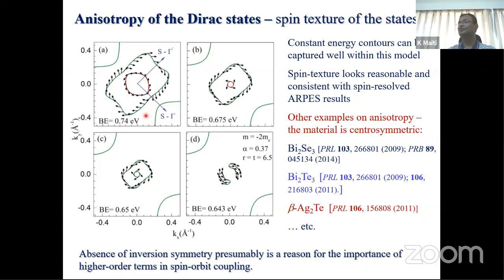Okay. So the conclusion that we can draw from this study is that the Dirac node that people have found so far in various studies is actually occurring at a S point, which has a finite momentum, not at the gamma point. And the anisotropy that we find can be explained by this higher order, which could be because of the lack of inversion symmetry in this material. That's our guess. But of course, we are looking at it much more in this material and trying to understand.